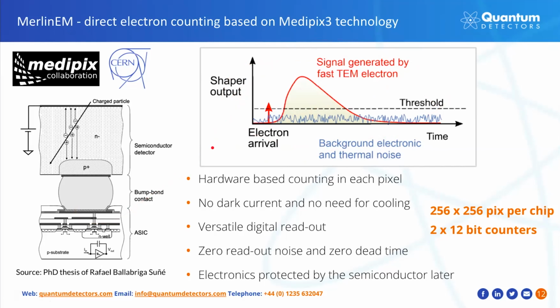And basically, the signal gets shaped and compared against the user-adjustable threshold. Only when the deposited energy is larger, so it overcomes this threshold value, the electron will be counted. This has many advantages. By applying the threshold, which is above the background electronic and thermal noise levels, we remove these unwanted contributions to the signal.